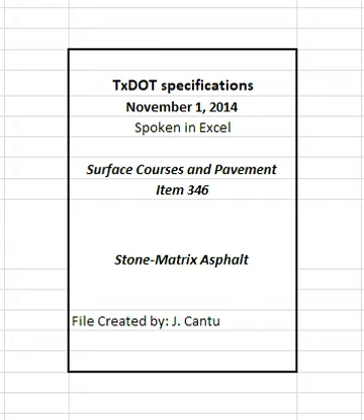Suspend production and shipment of the mixture if the engineer's VMA result is more than 0.5% below the minimum VMA requirement for production listed in Table 7. In addition to suspending production, the engineer may require removal and replacement or may allow the sublot to be left in place without payment.